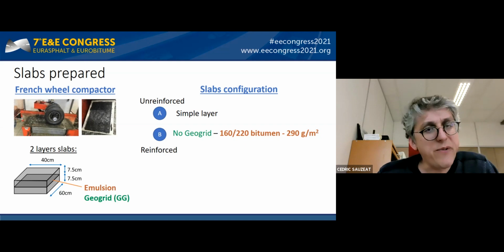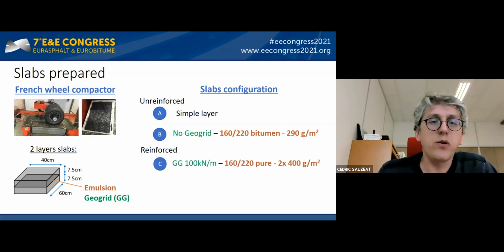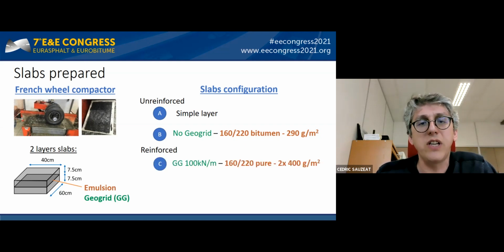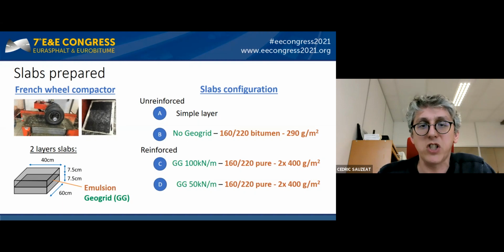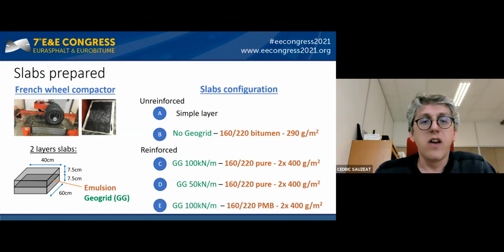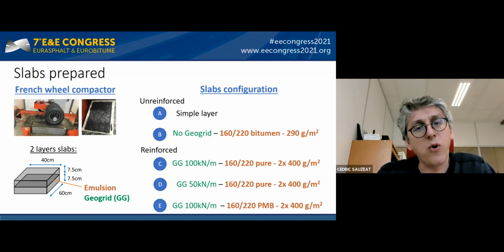Then we have three reinforced slabs. The first one is made with a 100 kilonewton per meter geogrid, and the same tack coat as the non-reinforced slab. The second one uses a 50 kilonewton per meter geogrid, same tack coat. And the last one uses a 100 kilonewton per meter geogrid, but the tack coat was made with the polymer modified bitumen.